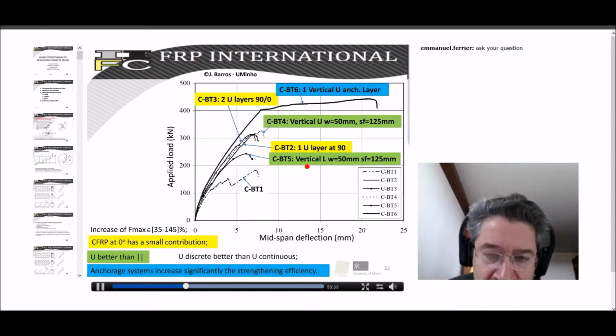And finally, we realize that when we introduce anchorage mechanisms, we increase the capacity significantly, and look, in this case, it was possible to transform a shear failure mode into a flexural failure mode.